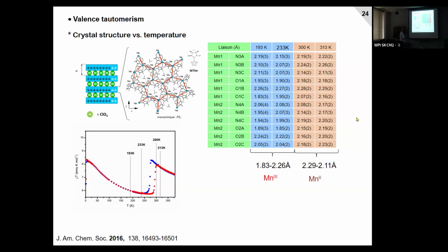And we looked at the manganese ligand interatomic distances. Here you see this value, which, I know manganese very well because I did my PhD on manganese, and this is very characteristic of manganese 2. The bonds are quite similar, at around more than 2 angstroms. So there is no doubt that here we have manganese 2. And then if we look here, we see that we have long, short, long, short. And here also, this is characteristic of manganese 3.